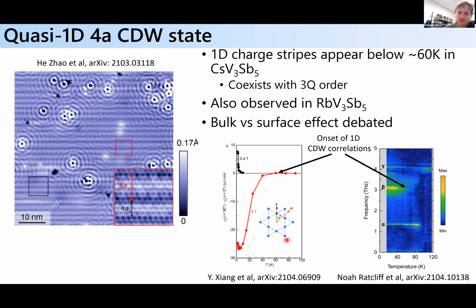And another potential piece of experimental evidence supporting this being a bulk effect is some very nice work from Hai-Hu Wen's group, where they're looking at transport along the c-axis, but then they rotate a magnetic field within the ab plane. So it's a transverse magnetoresistance measurement, and they look at the anisotropy of that as you cool down. And so basically what they find is there's some C3 symmetry breaking as you cool below 60 Kelvin or so in the cesium vanadium-3 antimony 5 system, which is also kind of supporting of some type of unidirectional, maybe nematic type of correlations forming.